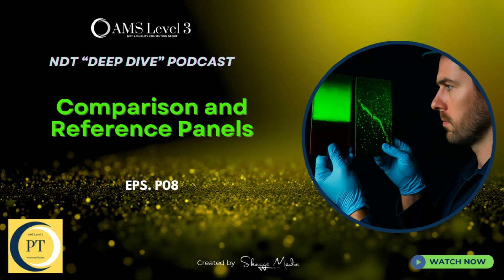It's not random. They aim for a specific aspect ratio, usually around 2:1, length to width. And that level of control is why they're used for the really critical stuff, like the Qualified Products List, QPL, AMS 2644, for classifying fluorescent liquid penetrant testing systems. Exactly that. For the official QPL stamp, they'll process, say, 5 of these specimens. Then they measure the luminance, basically the brightness of the indication, with a photometer. And that measured light output compared against a known standard, that's what determines the classification.